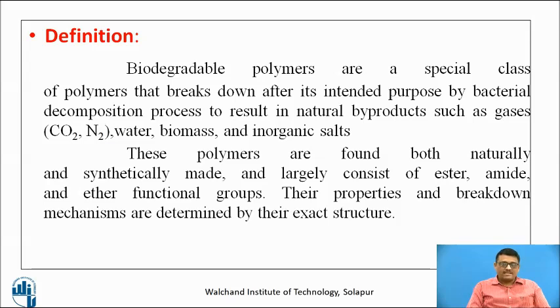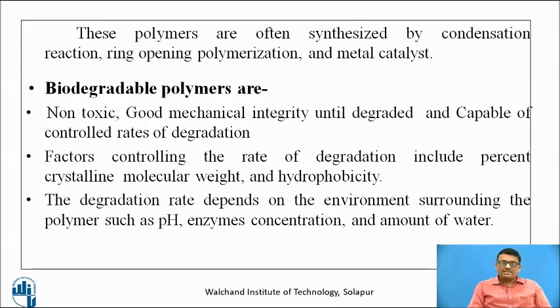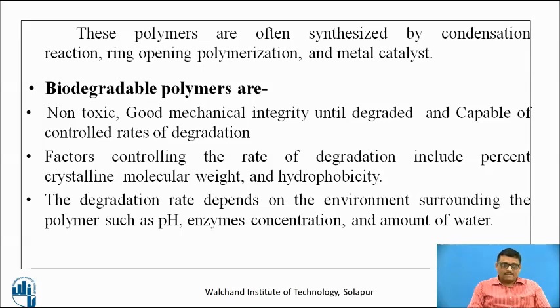Their properties and breakdown mechanisms are determined by their exact structure. These polymers are often synthesized by condensation reaction, ring opening polymerization, and by using metal catalysts. Biodegradable polymers are non-toxic, maintain good mechanical integrity until degraded, and are capable of controlled degradation rates. Factors controlling the rate of degradation include percent crystallinity, molecular weight, and hydrophobicity. The degradation rate also depends on environmental conditions such as pH, enzymes, concentration, and amount of water.